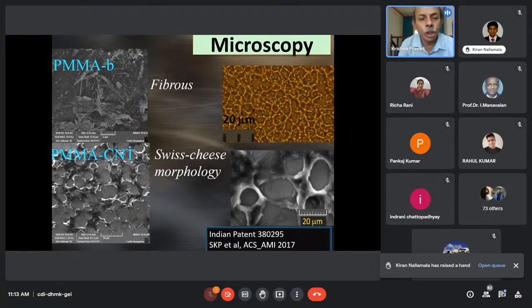I already showed the Swiss cheese architecture for a PDLC, and I also showed for the polymer stabilized system a fibrillar morphology. Again, I'm showing a similar kind of thing here. For PMMA, for example, you have a fibrillar morphology, whereas when you incorporate CNTs, you end up with a droplet morphology. Please recall, we had PDLCs which showed the droplet morphology, which is because of the rigidity of the system.